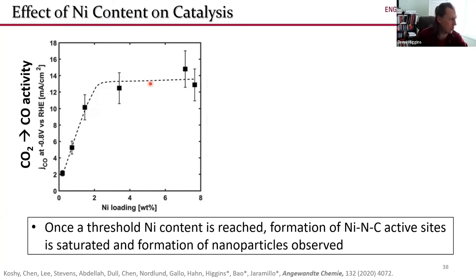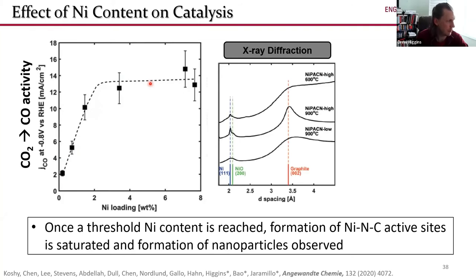So we wanted to figure out why. And essentially what we found is that when the concentration of nickel used during synthesis was relatively low, we did not see the formation of nickel particles, whether that's metallic nickel or nickel oxide.